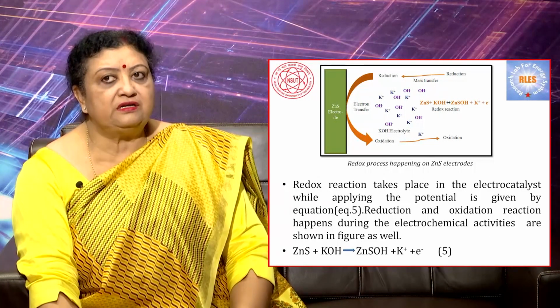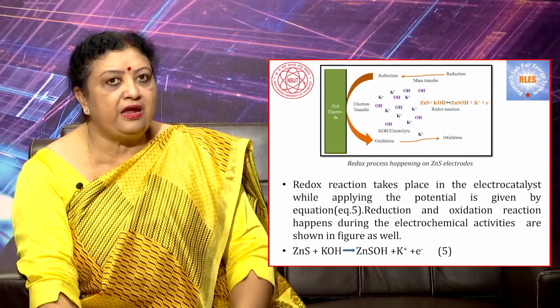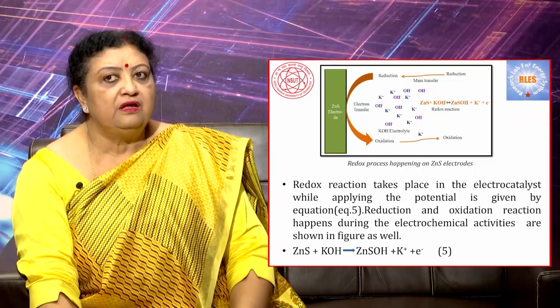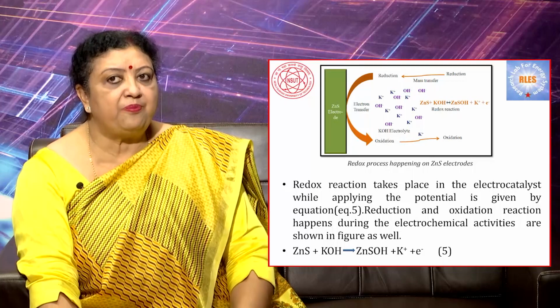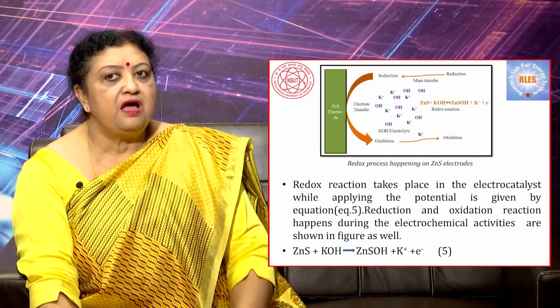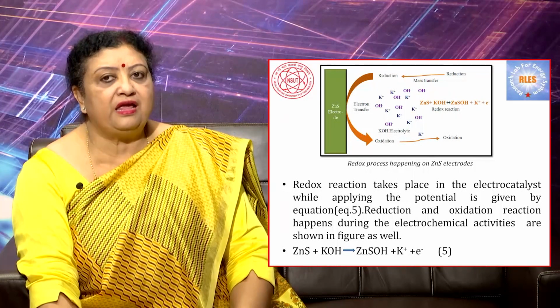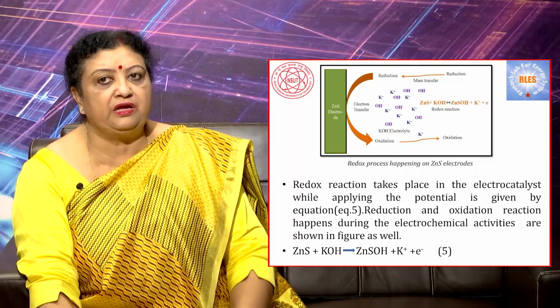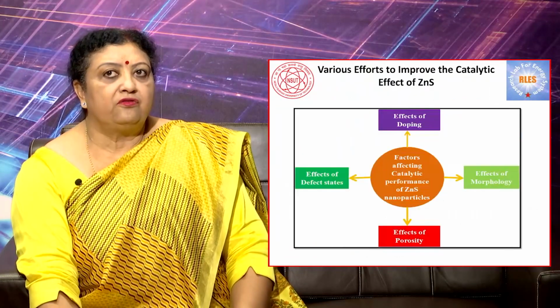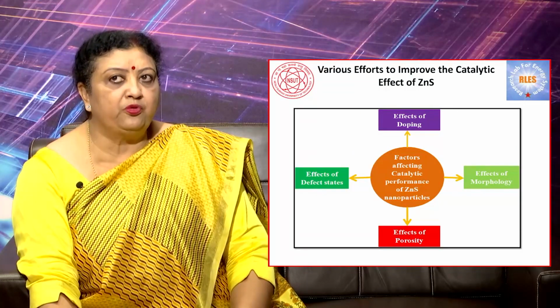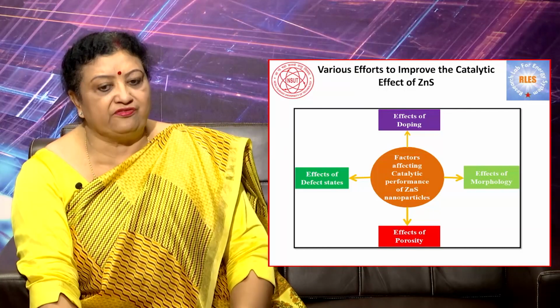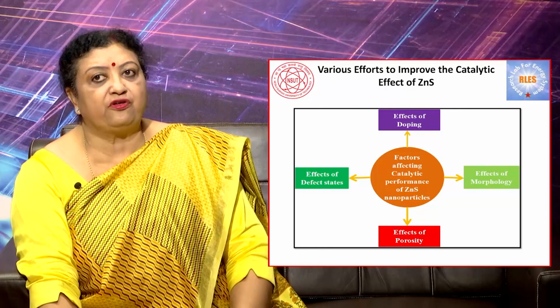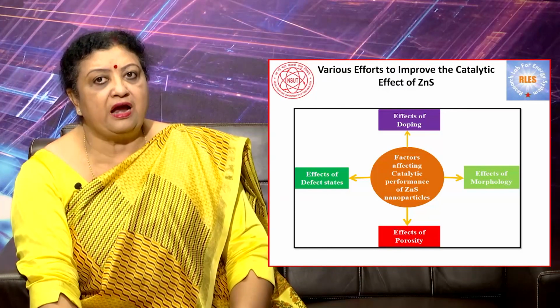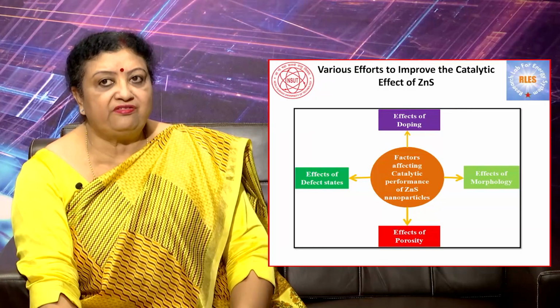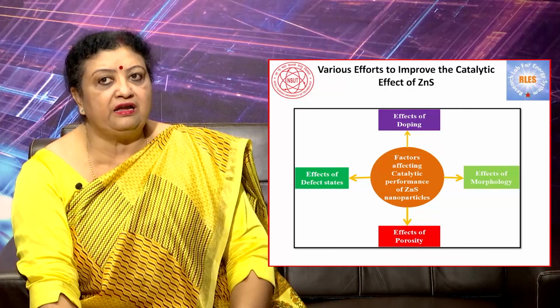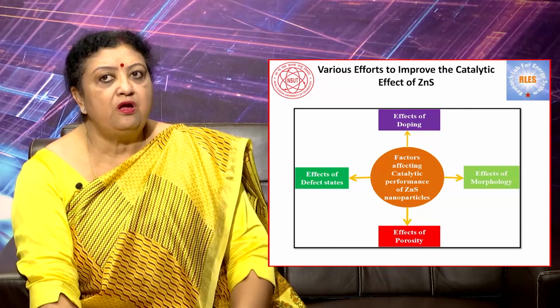So, the redox reaction that takes place in the electrocatalyst while applying the potential is given by the equation. Reduction and oxidation reactions happening during the electrochemical activities are shown here in the picture as well, and the reaction which is taking place has also been shown here. Various efforts have been taken to improve the catalytic effects of ZnS: the effects of doping, effects of morphology, effects of porosity and the effects of defect states. These are the factors which are affecting the catalytic performance of ZnS nanoparticles.